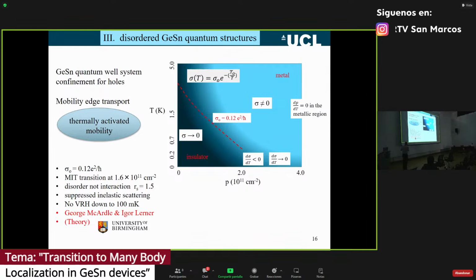So just to summarize this set of data that I've shown you, we've got this confinement for holes in this system. It's very clearly got a mobility edge. It's all thermally activated, but there's no hopping. We've got a false color plot here of this area of low temperatures and low carrier densities. This is carrier density in units of 10 to the 11, and this is temperature in Kelvin. This side we've got a metal. At low temperatures, the conductivity doesn't go to 0. We've got this thermally activated conductivity.